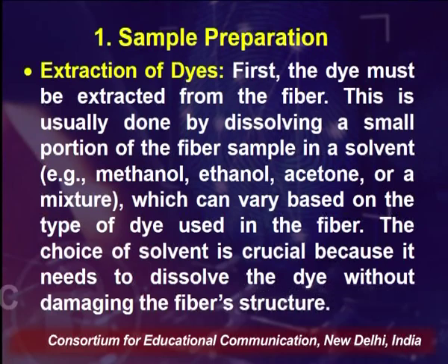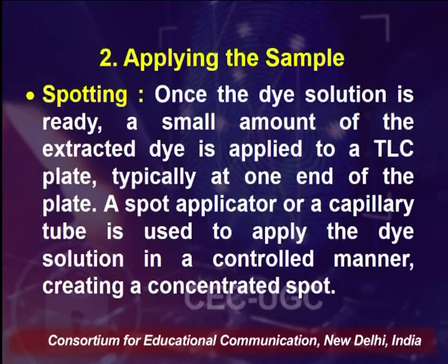plate. So, the first step would be sample preparation. The second step would be applying the sample. We can spot a sample using a capillary tube. A thin capillary tube can be used, or we can use a spot applicator. We have to make a concentrated spot at a particular position. That means the sample from the dye mixture can be added repeatedly, 4, 5, 6 times, so that the spot is concentrated. That means the amount of sample which we have on the TLC run